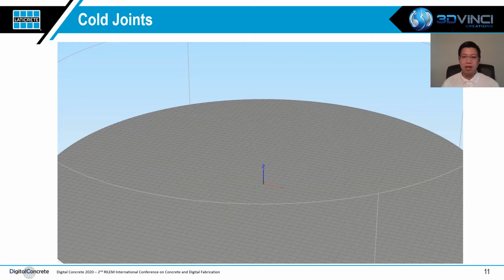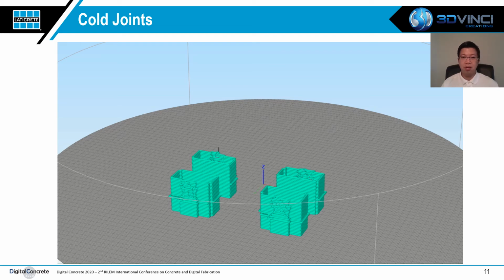When we print a large area, which commonly happens in a project, sometimes it is unavoidable to have cold joints. In 3D construction printing, a cold joint is a plane of weakness in mortar or concrete caused by an interruption or delay in the printing. It occurs when the first batch of mortar has begun to set before the next batch is printed on top of the first batch, so that the two batches do not intermix.